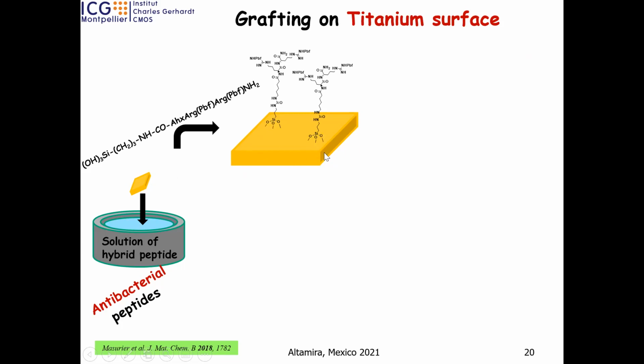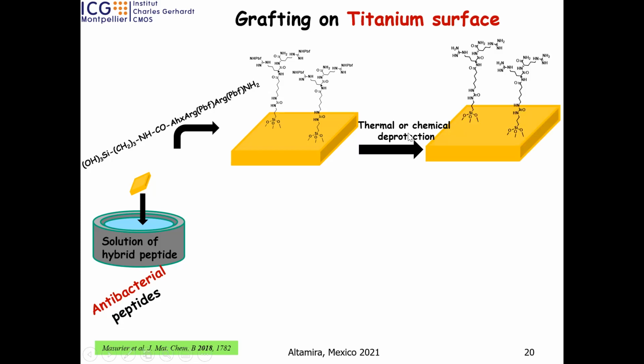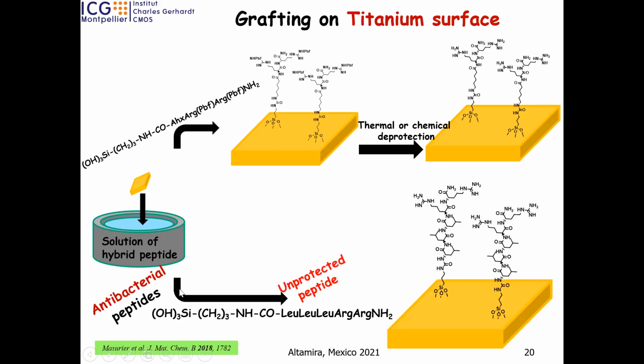Here I summarize it. It's 1 centimeter by 1 centimeter. We prepare at least 20 substrates, very small substrates. And by thermal or chemical deprotection, you can recover your peptide, and here another type of peptide, unprotected peptide. It's just to show you it's possible to take protected or unprotected peptide. In both cases, it was possible for us to immobilize it on the surface.